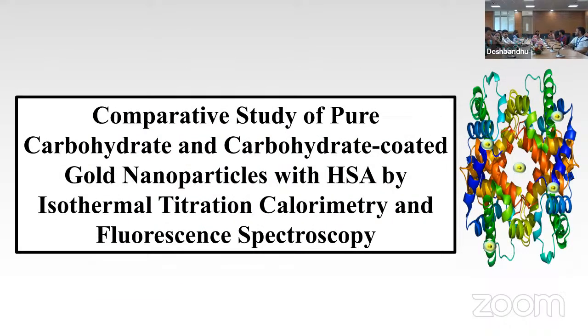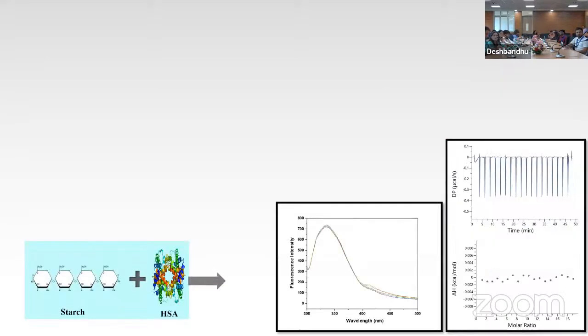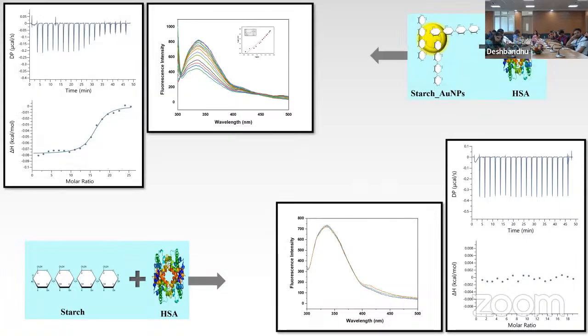Now similar studies were performed with pure carbohydrate and carbohydrate coated gold nanoparticle with HSA, and this was also done by isothermal titration calorimetry and fluorescence spectroscopy. The interaction between pure starch and HSA was studied by ITC as well as fluorescence spectroscopy. In this study, HSA does not interact with pure starch, so we concluded that negligible heat will be observed. So this is the profile for starch, and the starch coated gold nanoparticle shows binding, and the complementary result was obtained by fluorescence spectroscopy.